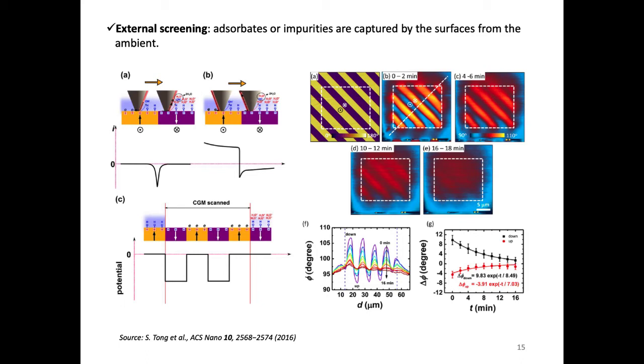And using charge gradient microscopy, Kelvin probe force microscopy, and electrostatic force microscopy, we can investigate the adsorption and desorption process by the atomic force microscopy tip, and also how they're being recovered as a function of time because of the thermal energy provided and the electric field, stray field, coming out of these crystals.